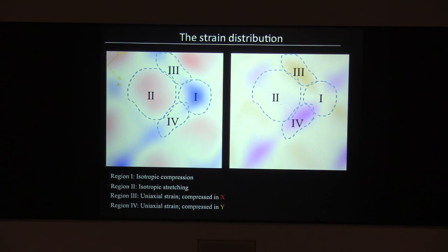So this strain calculation is just based on the topography? Purely, no. It's looking at shift in atomic positions. We don't look at the slope. That would be a little tricky. We actually look at the picoscale shift in the atomic distance. You have some algorithm to calculate that? It's the same algorithm that we use for correcting drift. It's our drift correction algorithm.